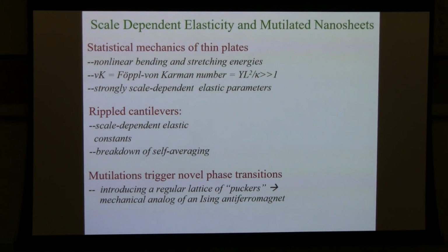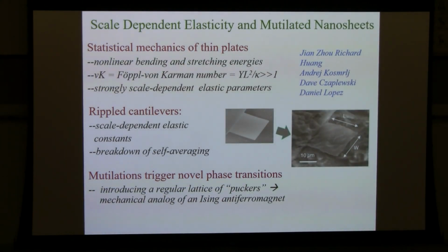I'll then move on to talk about, there's a prediction here when you turn on thermal fluctuations of strongly scale-dependent elastic parameters. And then I want to talk about this new class of aluminum oxide rippled cantilevers that my experimental colleagues have been making by templating off, it turns out, off a silicon wafer. And you'll see where that comes in a minute. And so they're able to make these diving board-like protrusions.